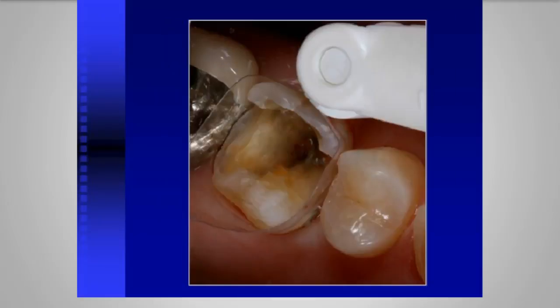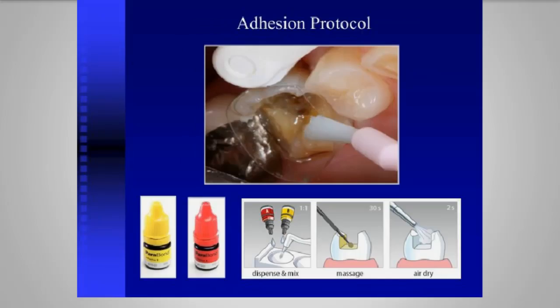Rinse and dry. Again, dentin shouldn't be totally dry. It should be damp. So if you over dry, I would re-wet with a cotton pellet with a little bit of water, any of the re-wetting agents that you want. This is the Parabond now. This is Parabond A and B.